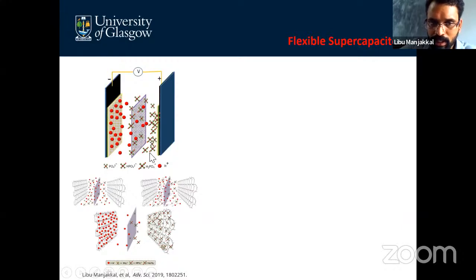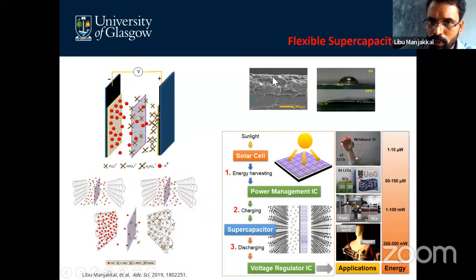You can see the cross section of this device: the top polyurethane, the graphene sheet, and the graphite polyurethane composite. Graphene shows a more hydrophobic nature, while graphite polyurethane, due to its rough surface, shows a more hydrophilic nature. Here again I integrated this with a flexible solar cell, and depending on my power application, for example to power an LED, meaning 1.8 volt or so, 1 to 10 microwatts, I can use it as a wristband. I converted this graphite polyurethane supercapacitor into a wristband, and it can operate almost 84 LEDs. And at 100 milliwatt power, for example to operate a motor which requires a voltage of 2.5 volt, I used this supercapacitor, and it is attached on the curved column here. You can see this yellow color.